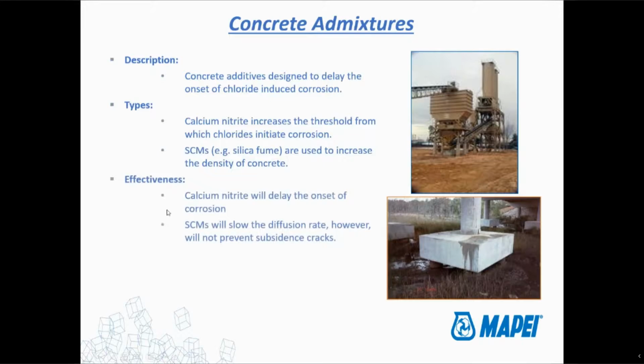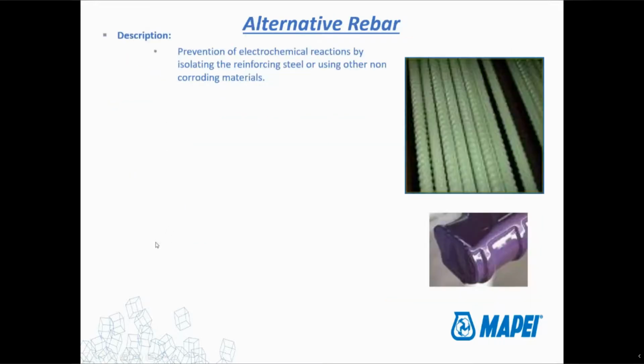So the effectiveness of these products, they're very effective as far as delaying corrosion. SCMs will certainly slow the diffusion rate as well, but it's not going to prevent subsidence cracks from forming. And once you get cracking, you're going to get more moisture intrusion, and the whole process is just going to be, it's delaying the inevitable, essentially. So it's a good, cheap thing that should always be added to really any concrete, just because it is going to slow things down, but it's not going to prevent corrosion in the long haul.